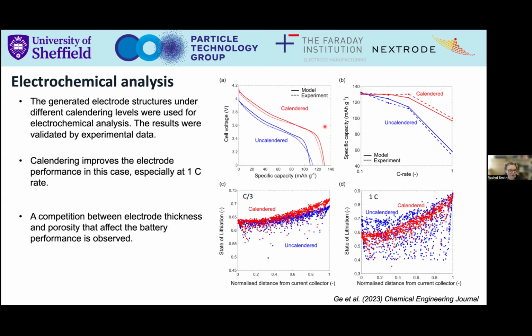And then, of course, we can look and see we've got different calendaring levels here. We can look at the state of lithiation between calendared and uncalendared electrodes. And of course, as you might expect, and this has been demonstrated, as we calendar our electrodes, what we do is we bring that distribution of our lithiation in tighter. So an uncalendared electrode, we have a much larger distribution. When you calendar it, you bring that distribution in tighter, basically.